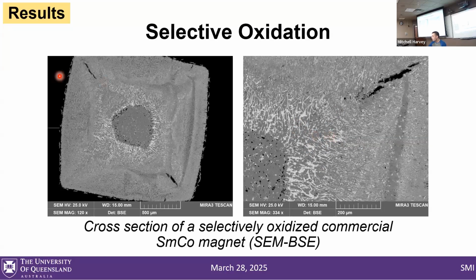Another interesting feature of the selective oxidation is you get this core of metal. This magnet has been fully oxidized for multiple days, and this is a core of copper, cobalt, and iron metal that segregates in the middle of this magnet. You can very easily break off the outer shell and get access to this nice meaty metal core. Unfortunately, to date...